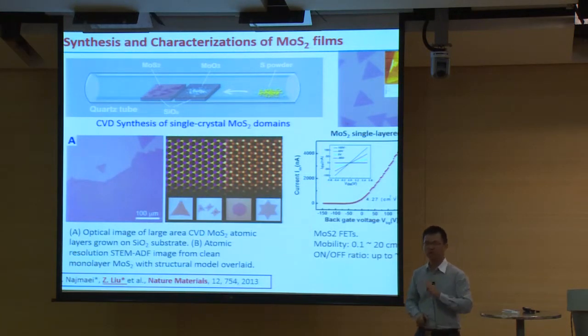Actually, oxide is really important for the synthesis of TMD materials, but I don't think anyone can get a very clear idea how it works. But it works for many of the TMD materials, tungsten disulfide, molybdenum sulfide. Maybe this is another story. Okay, from this method, we can get the single layer, single crystal molybdenum sulfide. And from the AFM height topography, the thickness is 0.7 nanometers.